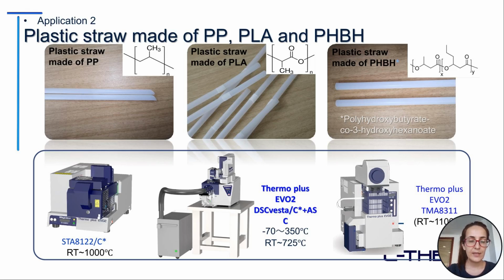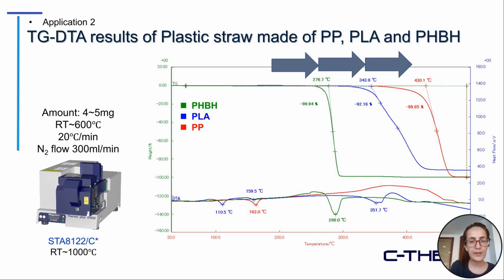Thermal analysis was carried out with the STA, DSC, and also TMA. First, we look at the TGA and DTA results of the plastic straw made of PP, PLA, and PHBH. In this example, we used 4 to 5 milligrams of sample heated from room temperature to 600 degrees Celsius with a heating rate of 20 degrees Celsius per minute in an inert atmosphere, under nitrogen flow.